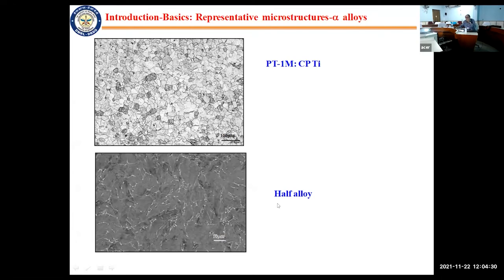Then there is another alloy, which is called a half alloy. Half alloy composition wise is half the composition of Ti6Al4V, and you can see very fine beta around the boundary. Rest is all alpha. This is a SEM picture.